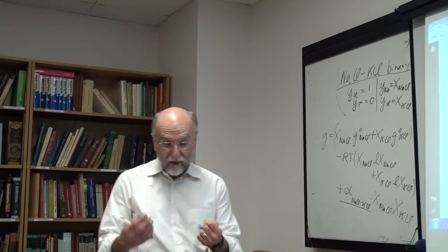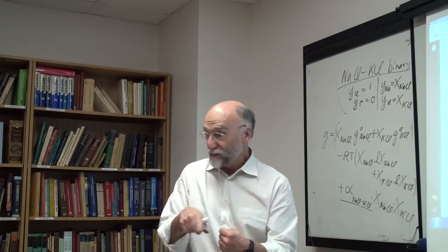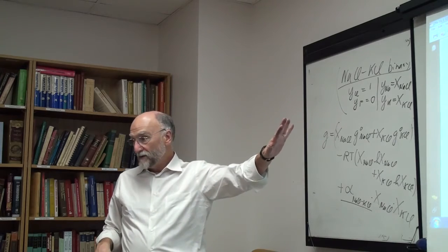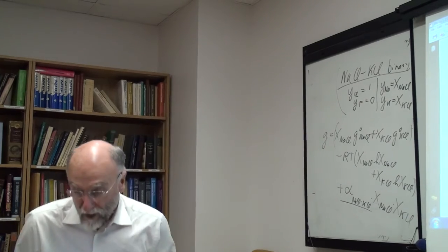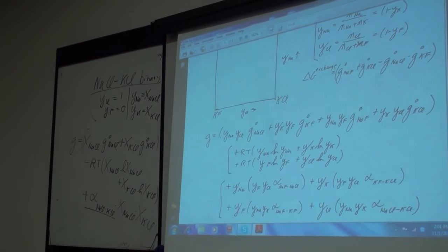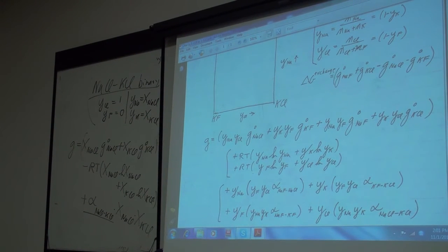Remember, the energy of the second nearest neighbor sodium-potassium bond is going to be different if there's a fluorine in between than if there's a chlorine in between. Okay, so it reduces exactly to the binary systems on all four sides, which we want it to do. So if you have data for all four binary systems, if you've optimized all four binary systems, and you have values for the G naughts as well, you can estimate the reciprocal salt ternary liquid using this equation.